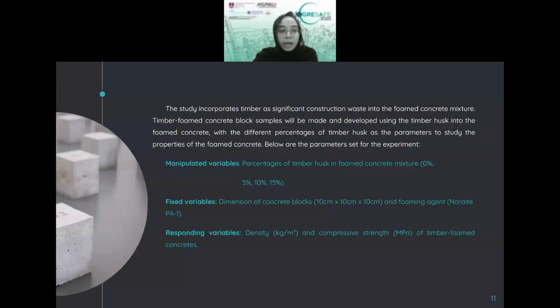As you can see, for the manipulated variable, I have different percentages of timber husk in the foam concrete mixture, which in this research paper, I use 0%, 5%, 10%, and 15% of untreated timber husk additive inside the foam concrete. And then for the fixed variable, I use the same dimension of the concrete block, which is 100 cubic millimeters.